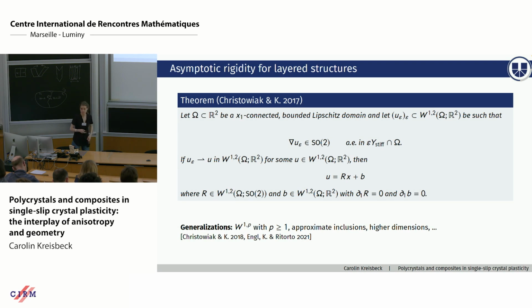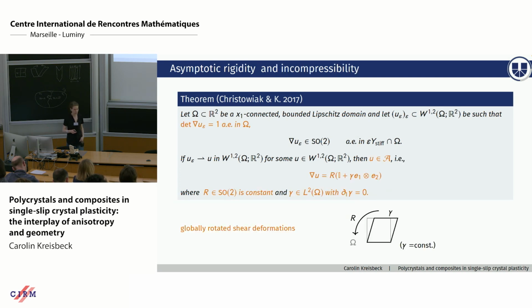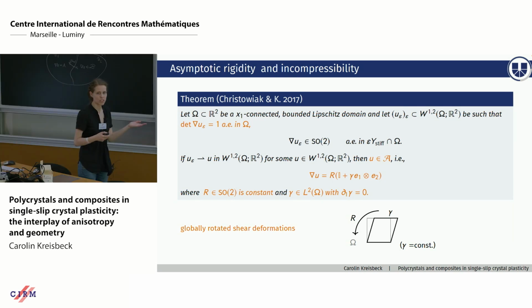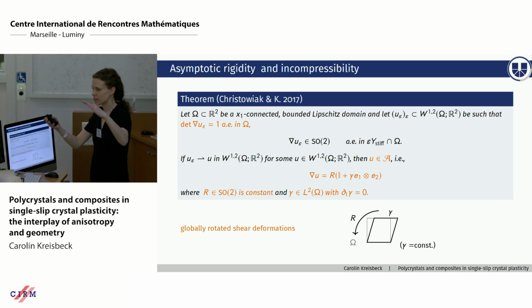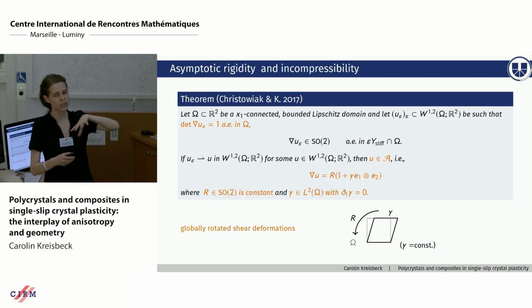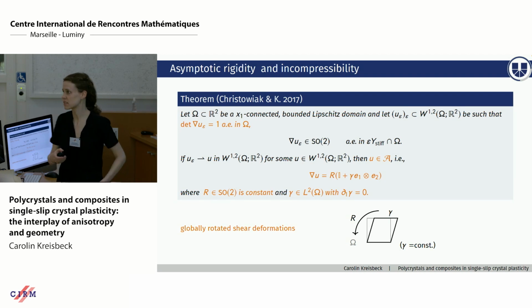Now if we incorporate more assumptions into the model, namely incompressibility or local volume preservation if you wish, so in any case we have that for our plasticity model, then we can prove even stronger restrictions on the limit deformations, namely that they have to lie in the set we call A, so they are globally rotated shear deformations. So you can shear in horizontal direction and then rotate everything globally. And formally, that means that the gradient of u is really a constant rotation times identity plus gamma e1 tensor e2.